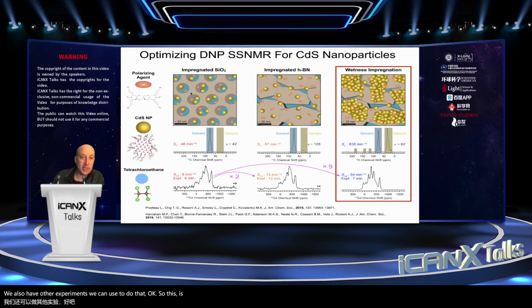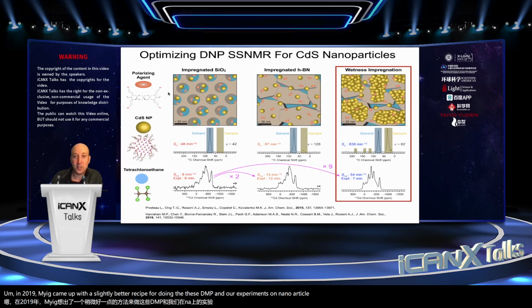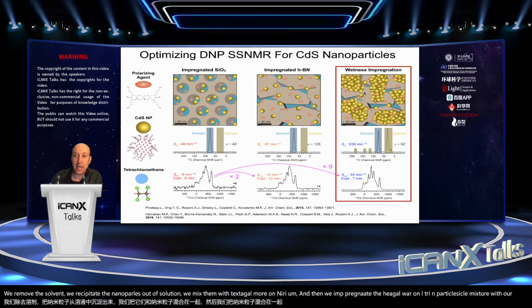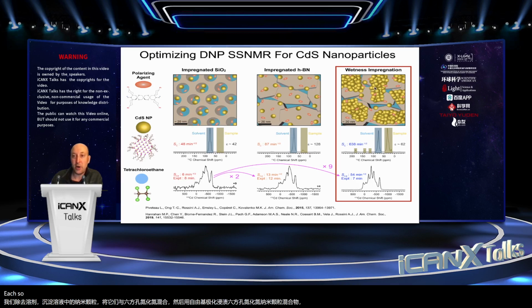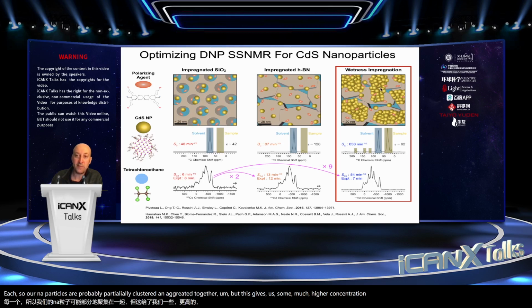Okay, so this is the initial way that we were doing DNP back in 2015. In 2019, my group came up with a slightly better recipe for doing these DNP NMR experiments on nanoparticles. I'll just skip over the details a little bit, and I'll just say the way that we do this now is we first take a solution of the nanoparticles, we remove the solvent, we precipitate the nanoparticles out of solution, we mix them with hexagonal boron nitride, and then we impregnate the hexagonal boron nitride nanoparticle mixture with our radical polarizing agent. So our nanoparticles are probably partially clustered and aggregated together, but this gives us a much higher concentration of nanoparticles in the rotor.